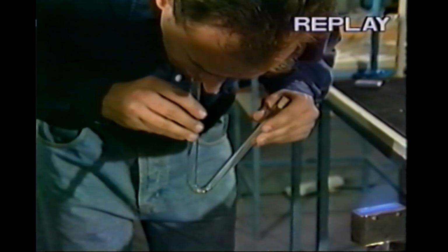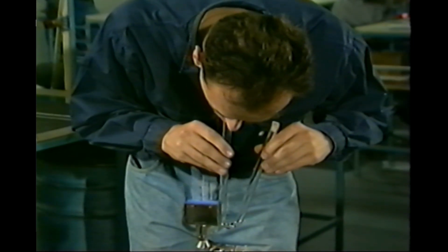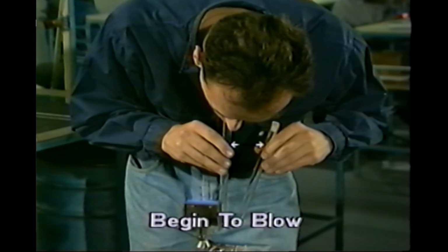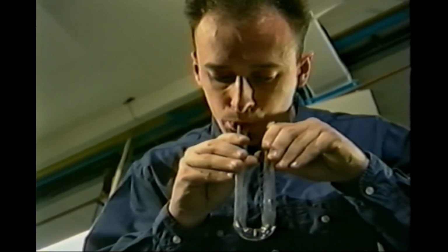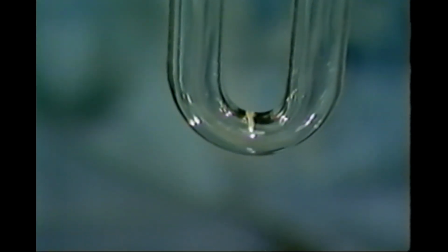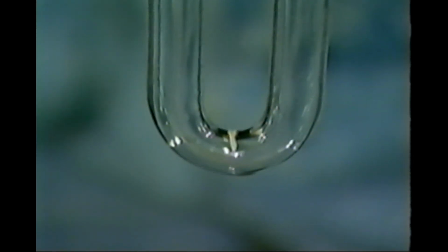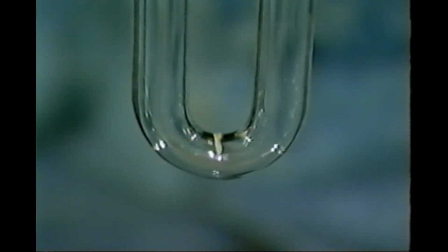This first shape and the correct area of melt sets up the distance between the two sidearms when the bending is complete, which should ideally be 1 tube diameter. Now bend the left sidearm, and when it has traveled half the distance between the 45-degree angle and parallel to the right sidearm, begin to blow gently into the tube. Keep the left sidearm moving and keep blowing until it's parallel to the right sidearm. The tube diameter, which will collapse due to the stretching during the shaping, will be restored.